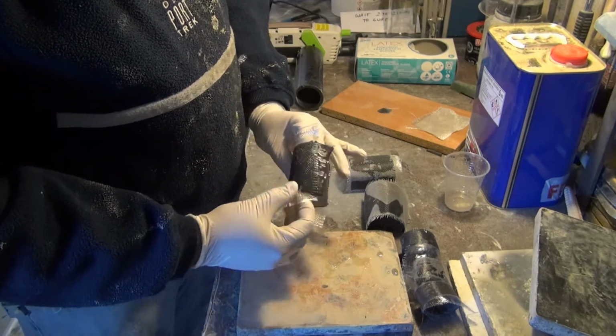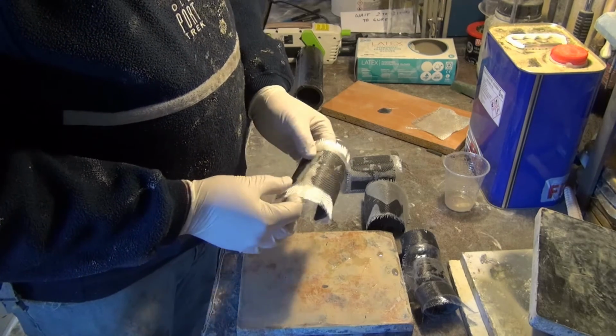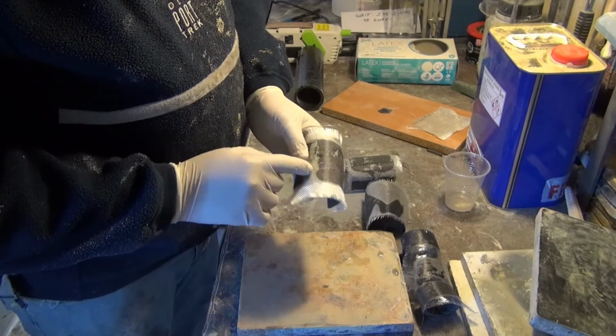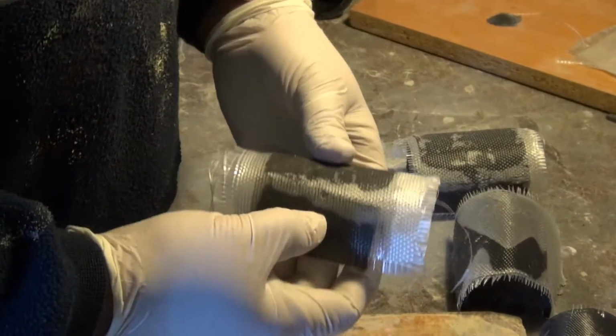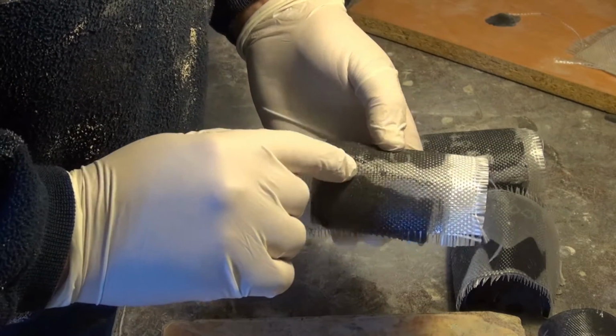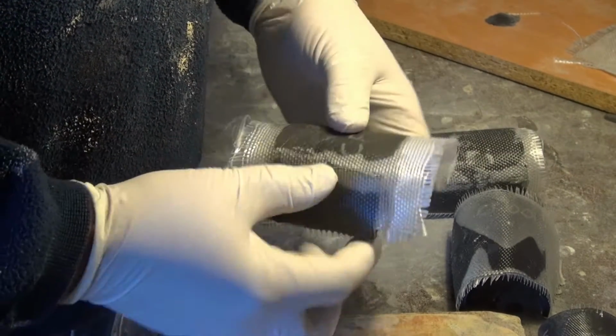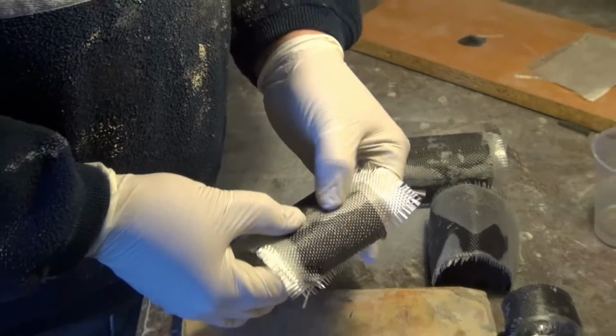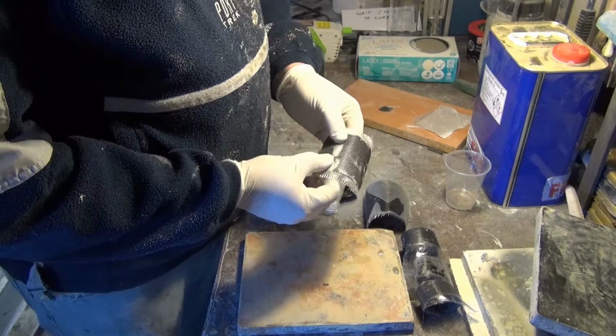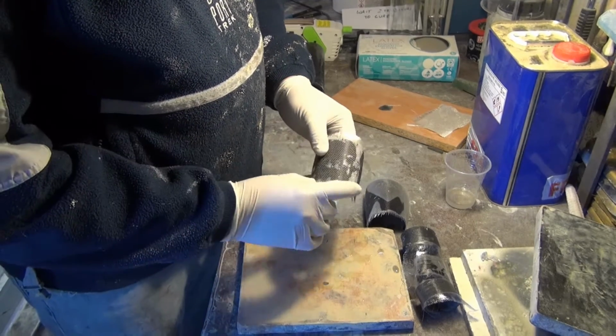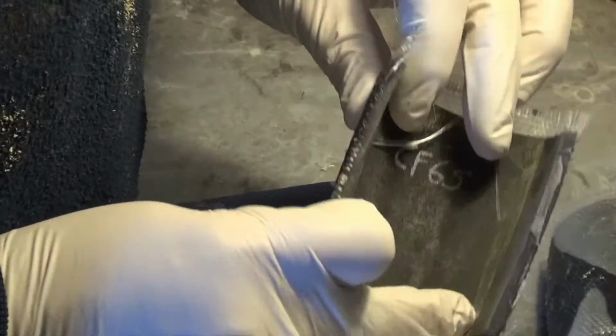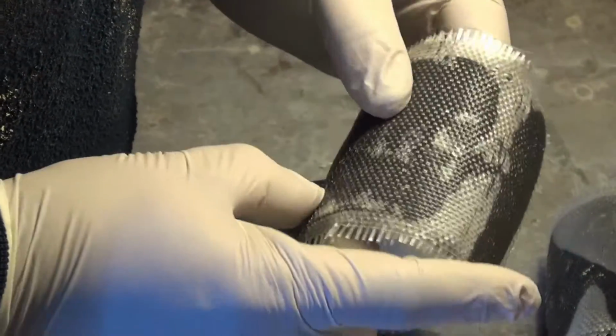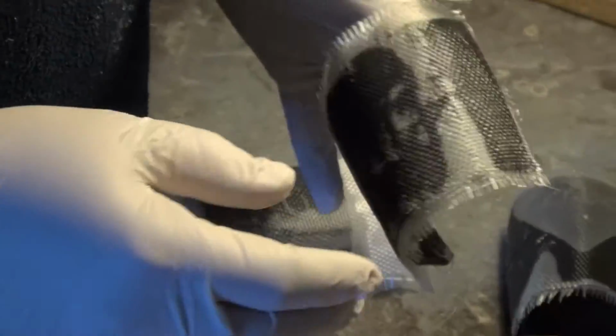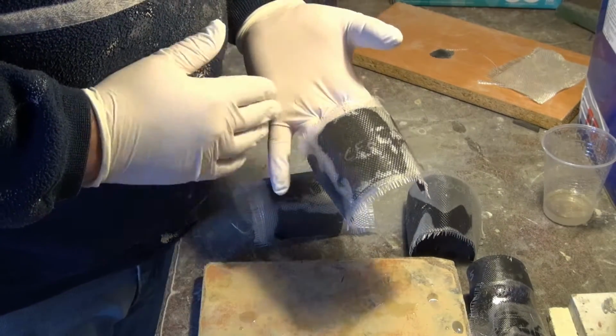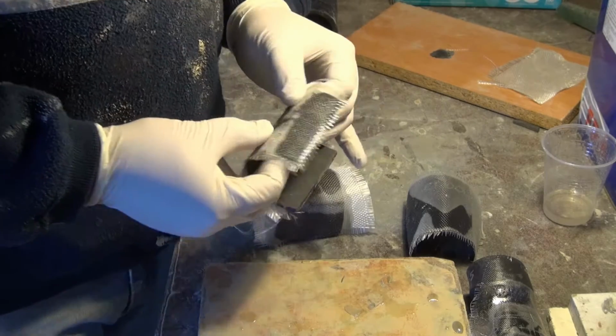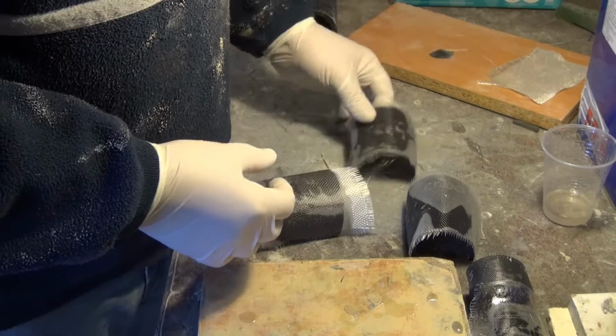On the craft foam sample, the fiberglass and resin have a good adhesion to the foam, but not to the area that has contact glue. The CF65 sample also shows a good adhesion of the fiberglass and resin to the foam, but not to the bonding areas, both the contact glue and heat joining lines. This problem can be solved by applying a layer of resin that is allowed to fully cure before applying the fiberglass.